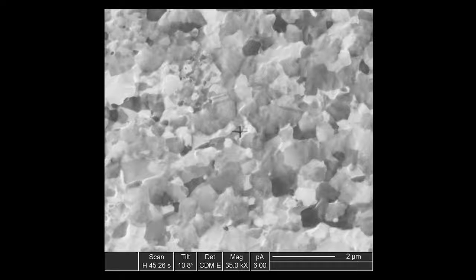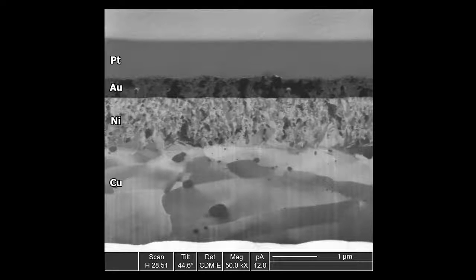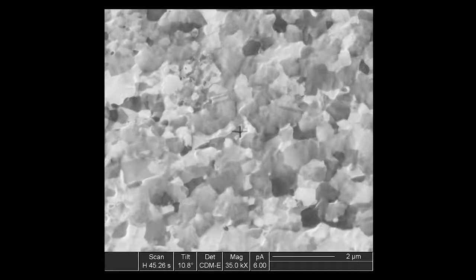And this is so that we can see why we get the grain structure contrast that allows us to see these layers so distinctively, whereas in an SEM they would look much more homogeneous and wouldn't have that distinctive grain structure in a standard SEM image. So the ion beam hits the surface of the sample and it channels in between the crystal planes. And so based on the angle each grain in the material is at, the ions can penetrate either more deeply or they don't penetrate as deeply, which affects how bright they appear.